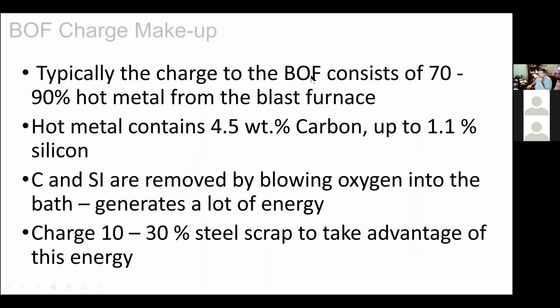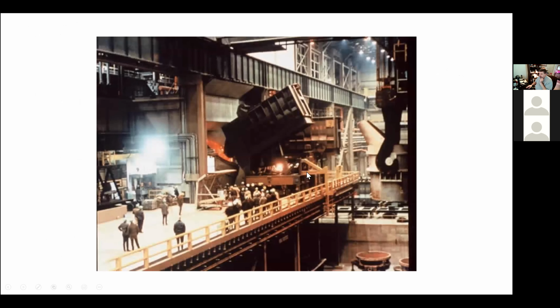As I said, the charge in the BOF typically consists of somewhere between 70 and 90% hot metal that comes from the blast furnace. And what we're going to do is remove all of the carbon and the silicon. In doing that, we generate a lot of energy, so we charge 10 to 30% steel scrap to take advantage of that energy. And here you can see a charging container. In BOF shops, they tend to be rectangular, and they load scrap in here with a crane somewhere back over here. And then they bring that in with the crane and they pour the scrap into the vessel in order to get ready to start the heat.